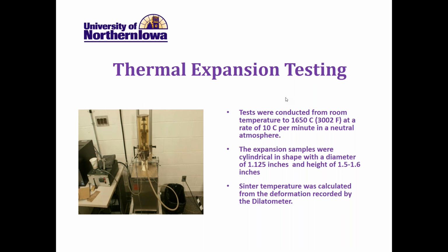To define the sinter point, it's the point at which we get liquid on the surface of the sand or the bead that allows those beads to adhere to each other. So if we've seen silica sand castings, heavy gray iron, we usually see a small adhering layer of sand that's easily broken up. That sand has exceeded the sinter point, so it adheres to itself.